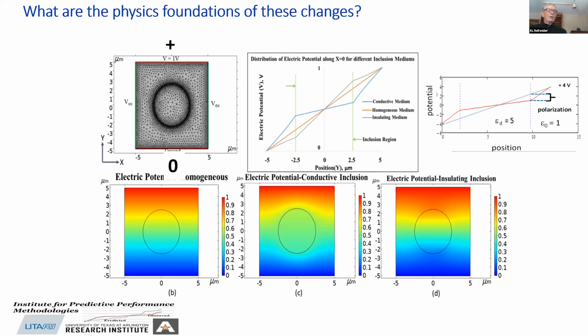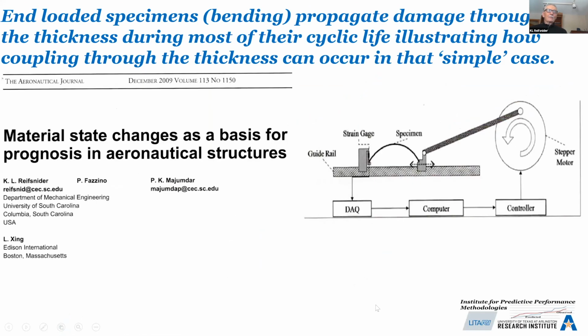And that's interesting. And if some material inside there is more insulative, less conductive than the center section, the slope will be greater because the change in voltage must be greater to make that thing constant if the other quantity is going down. So what happens at the interface? There is an abrupt change in the rate of change of voltage across that interface, which is, by classical definition, a charge, a collection of charge, a polarization, if you will, as shown on the top right. We've done these experiments, we know it works, and so we can use this as our starting point.